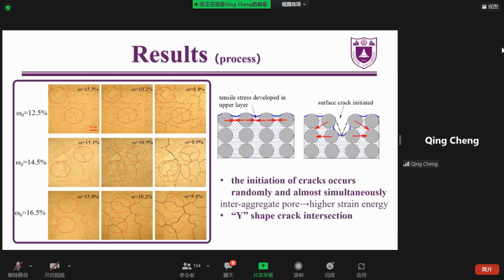And from one crack initiation point, the three cracks propagate in three directions with an angle of 120 degrees, resulting in a Y-shaped crack intersection. And this can be explained by adopting the concept of Griffith's fracture energy balance. The Y-shaped crack intersection is the most energy efficient, where the crack length required is minimum for expanding the same amount of energy.